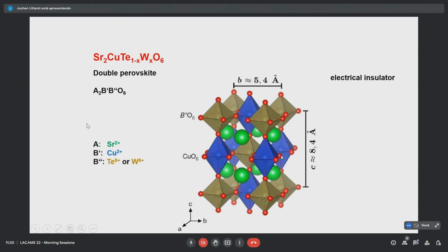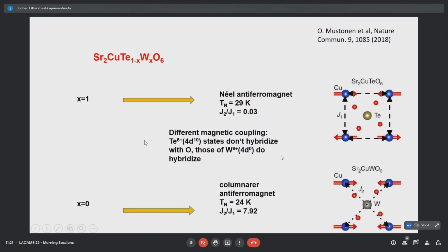Now, the structure, you see, that's a double perovskite. The major ingredient, that's the copper, that's the magnetic part of it. The copper that's sitting here on the blue side. So the main motif, that's a square we have here. The yellow ones, the rest, that's tellurium, respectively, tungsten. Now, electrical insulator again. What's interesting in that system, if you take the pure system, if you go to the pure tellurium system, that's X equal 1 in the structure, you will have a dominant nearest neighbor interaction, antiferromagnetic.